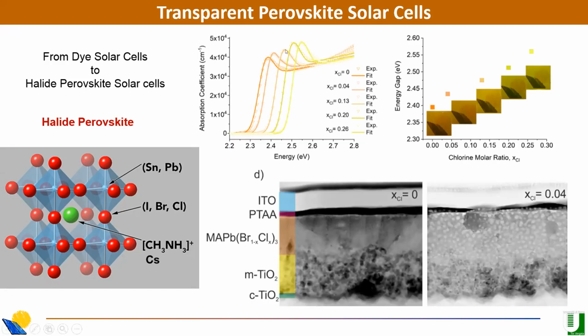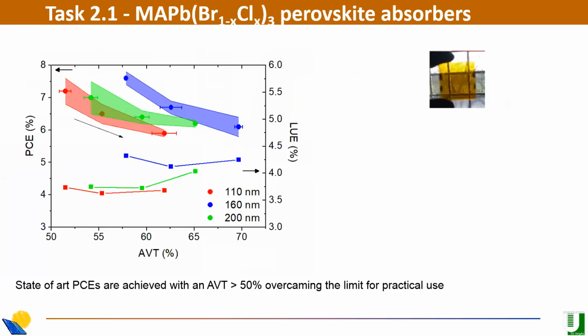And then indeed you can see here, in the first plot, I show you the absorption coefficient as a function of the energy of the photon for different concentrations of chlorine. I'm now focusing on this kind of perovskite, methylammonium lead bromine chloride, because it has a large gap for making a UV absorber. As you can see, changing the chlorine content, you can change the gap from 2.4 to almost 2.6 electron volt. So you are moving the gap toward blue or near UV. This is what you can get with this perovskite absorber.